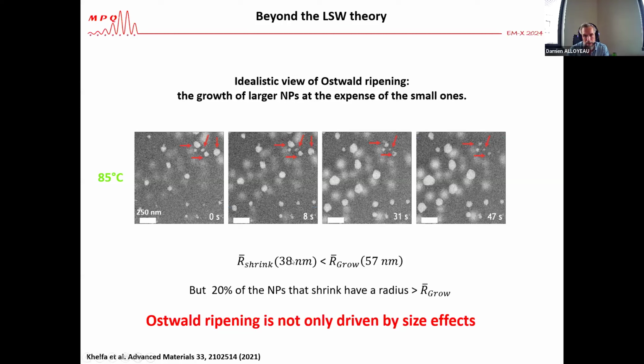On average, if you take the mean size of the nanoparticles that shrink, it's smaller than the nanoparticles that grow, but more than 20% of the nanoparticles that shrink have a radius much over these 57 nanometers. So it tells us that there are other parameters that are involved in Ostwald ripening. It goes beyond size effect.